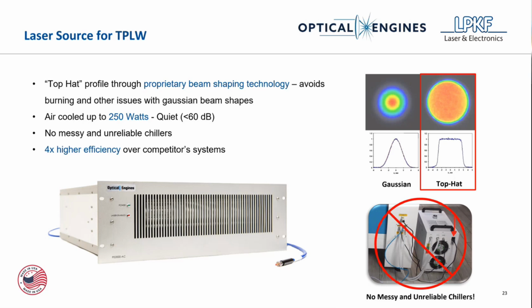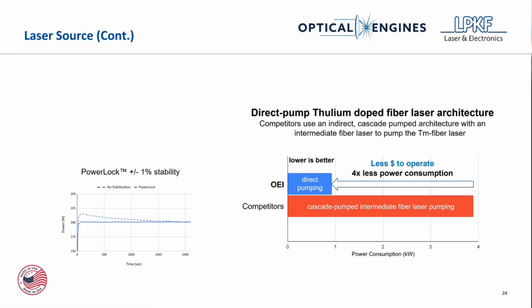And roughly 4 times higher efficiency over competitor systems. And I'm going to go into that here. The reason for that is it's a direct pump thulium doped architecture, whereas competitors have this cascade pumped. So this is the main reason to it being literally 4 times less in power consumption, much, much more efficient. And they are able to get up into this 250 watt range or even more, actually.